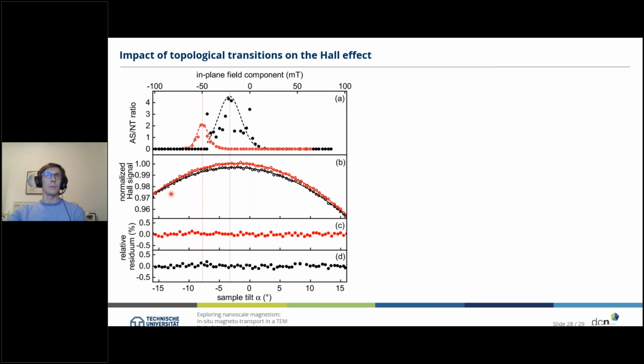That very well fits. But if you look here at the appearance of the anti-skyrmions, either at the black or at the red curve, we see no deviation of the Hall signal with the appearance of anti-skyrmions, which have a topological charge. We can also subtract that cosine here, which gives then the relative residuum, but also there is no correlation between the appearance of anti-skyrmions and the residuum, subtracting simply the cosine behavior.